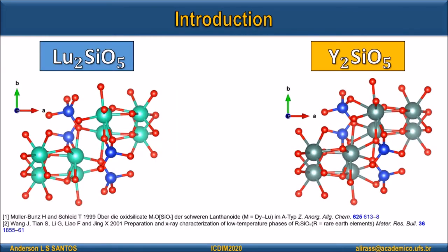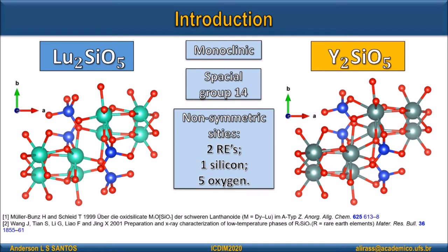Different types of structures are found for these materials in the literature, and for this work we use a monoclinic structure with space group 14, with 2 rare earth non-equivalent sites, 1 for silicon and 5 for oxygen, for both structures.